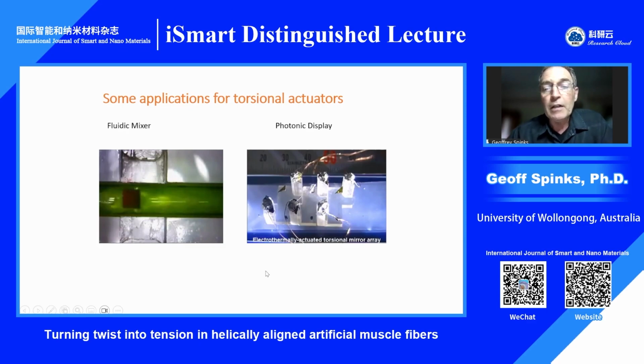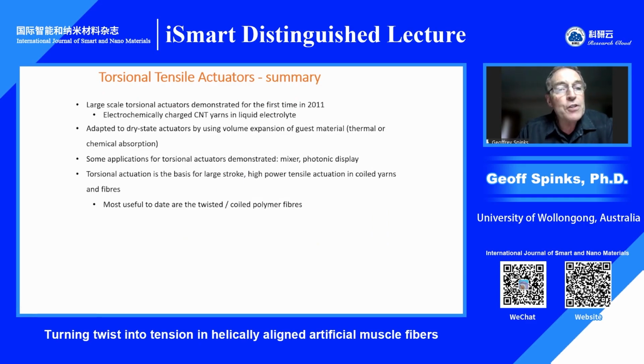In other work that we did in collaboration with Professor Sunjong Kim at Hanyang University in Seoul, Korea, we attached little mirrors to these yarns, and they could operate as some type of photonic display. So there were some applications for these materials, but perhaps a little bit limited. To summarize this part, just over 10 years ago, this large-scale torsional actuation was demonstrated for the first time, and then it was quickly adapted to other materials and in a more practical dry state setting. But it should be said that the real main application for these torsional actuators is being the basis for the large tensile actuation occurring in coiled yarns. And that's what I'd like to now go on to talk about.